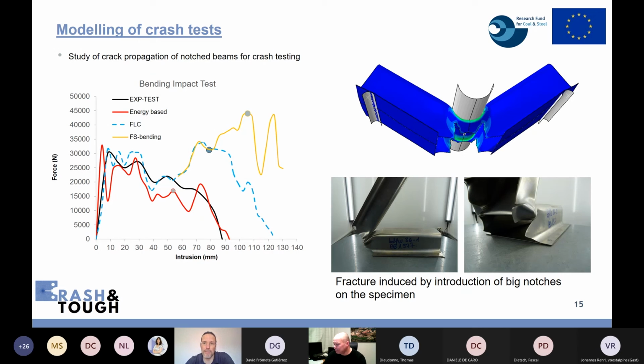Also, we did a simulation with the bending fracture strain, obtained in the bending condition. It is the yellow line, but this criterion is more convenient to use when we have positive to negative strain along the thickness in a pure bending condition. And here the failure is under full tension in the lower part of the specimen. For this, the energy was overestimated with this model. In conclusion, we showed an improvement of around 40% using our model in comparison with the conventional FLC. Of course, the FLC is a good tool, but in this case, it's too conservative in terms of energy absorption.